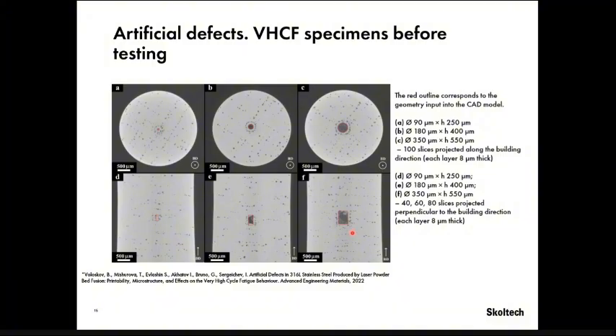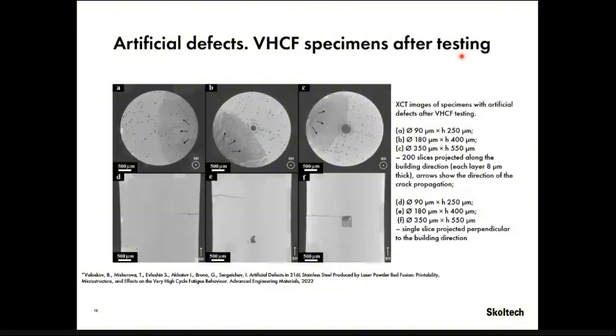So this red outline is the CAD model, and this is XCT results. It is worth noting that this is like 100 layers projected here, so the porosity is not so high as you might think. And also, we tested the specimens in a very high cycle fatigue regime,